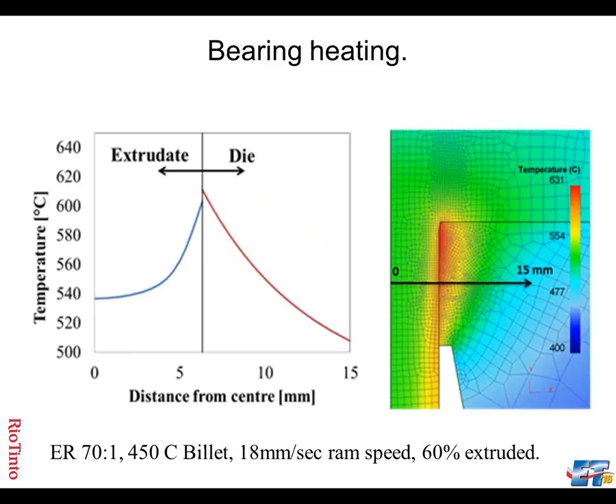And this illustrates it and demonstrates the difference. It shows that all the heat is being generated, and you say, why is this so hot at the entrance and not the back, considering there is continuous shear on the bearing surface? It's mainly because the die is not uniform, and the back of the die, the exit side of the die, is colder than the die face. We have a perpetual supply of hot metal coming in, adding heat.